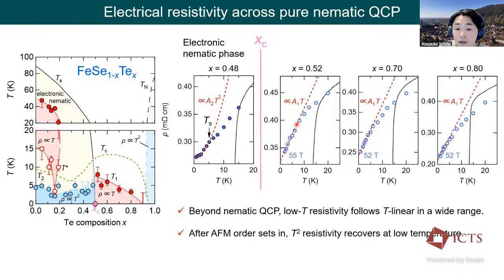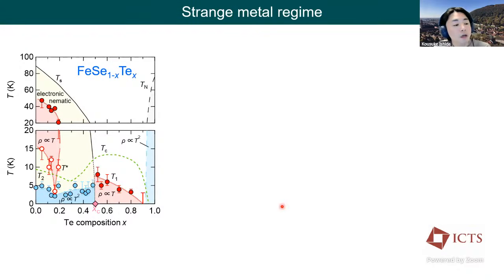So away from the QCP, the onset of T-linear resistivity decreases, but it keeps following T-linear. After entering the antiferromagnetic order close to the iron telluride side, the T-square resistivity is restored at low temperatures. So we have found two T-linear resistivity regimes in the phase diagram. Both of them are observed at sufficiently low temperature, so this cannot be ascribed to phonon scattering, so they can be taken as strange metallicity originating from electron scattering.